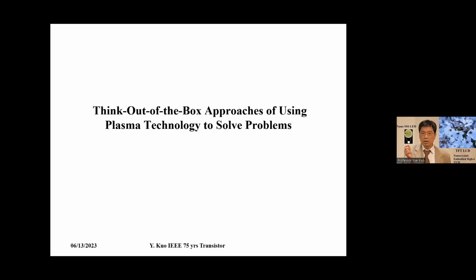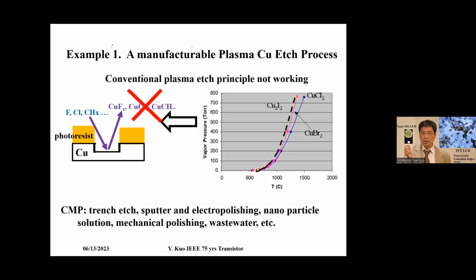Then beyond the manufacturing process, high plasma technology can be used to solve some long-term problems, of which I'll give a couple of examples. First, copper etching by plasma. It has been 60 years since we first introduced semiconductor fabrication, and people had the idea of etching copper with plasma. It doesn't work. Very simple, because the conventional wisdom of etching copper is to form a volatile product, but copper halide or organic compounds have low vapor pressure unless you heat up to a high temperature. This bothered the field and production for 60 years, until IBM introduced CMP, chemical mechanical polishing. That's widely used in industry.